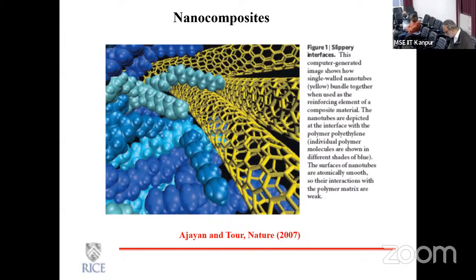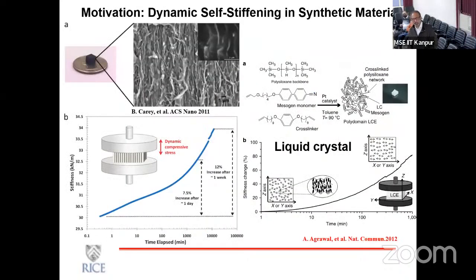Again, nanocomposite is another area that we have worked on for a long time. I'll skip this. But again, I wanted to point this out because in many of these scenarios you might get things that are quite unexpected. What we did was we created this carbon nanotube polymer composite, and we were doing dynamic loading on this material. We found that the stiffness actually is increasing with time rather than decreasing.